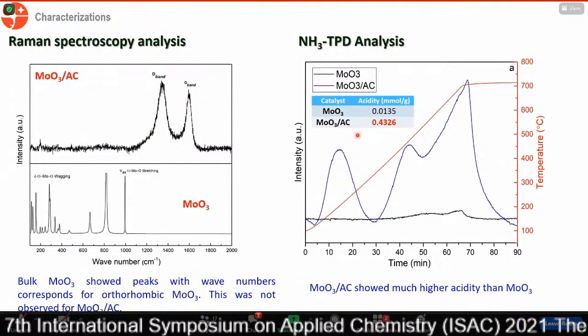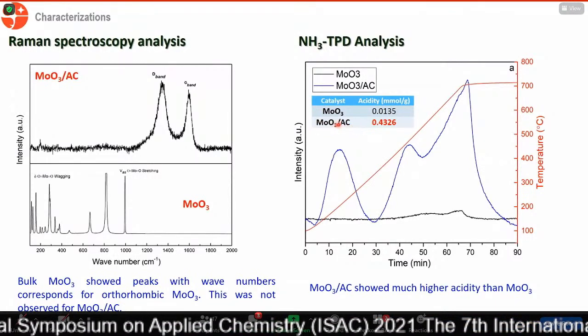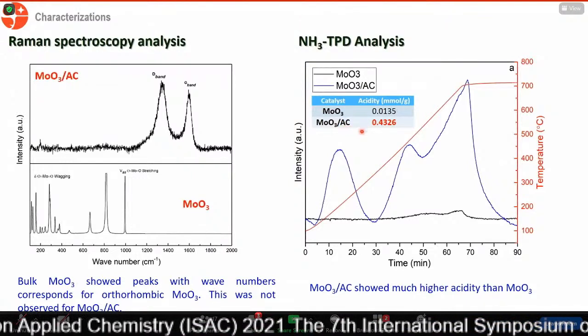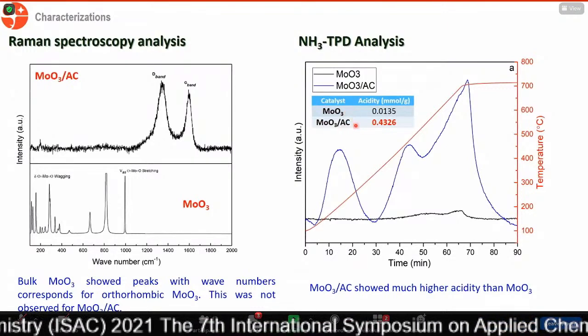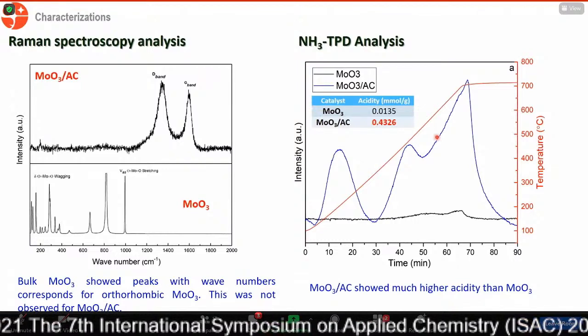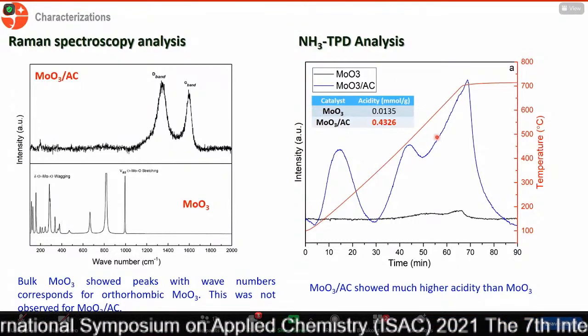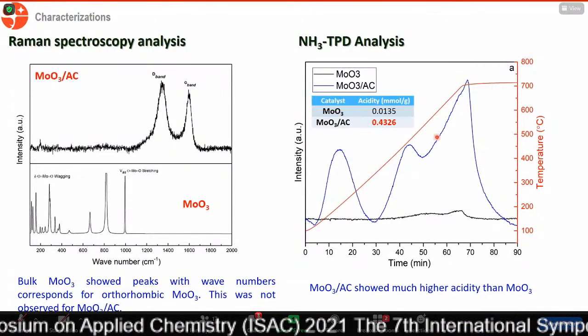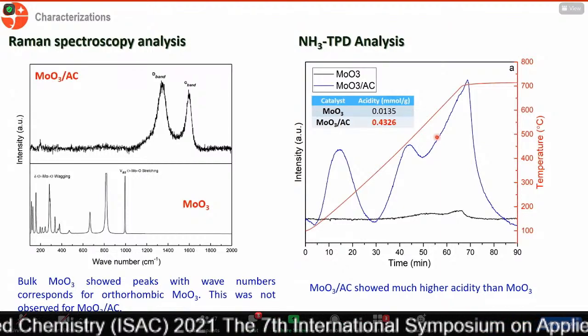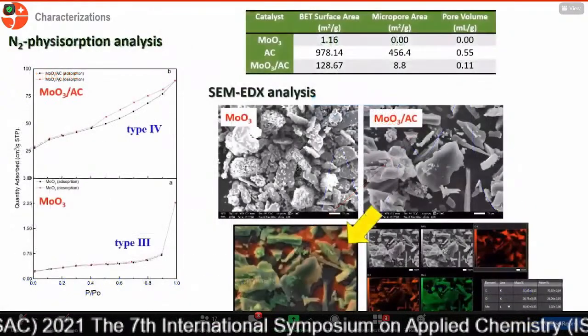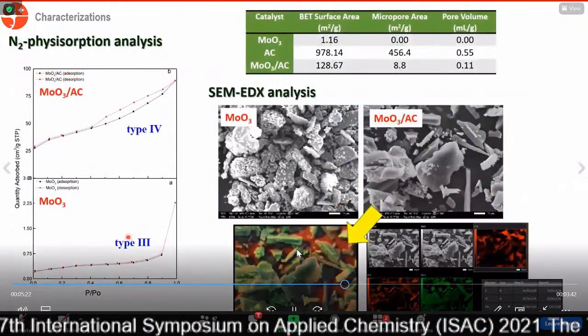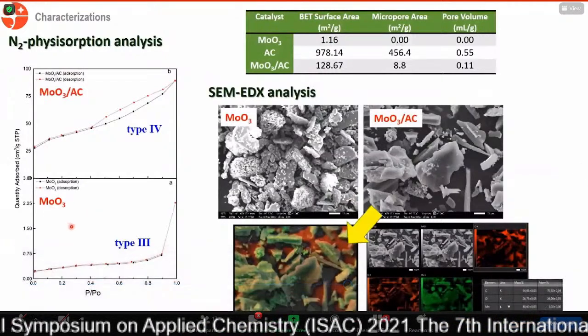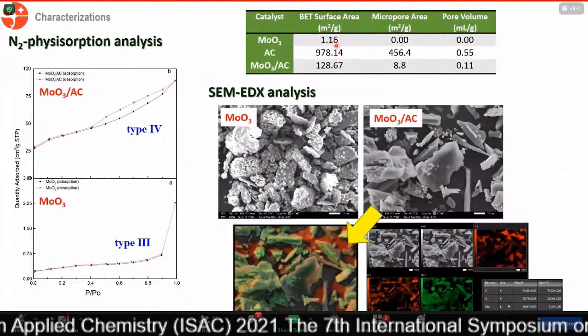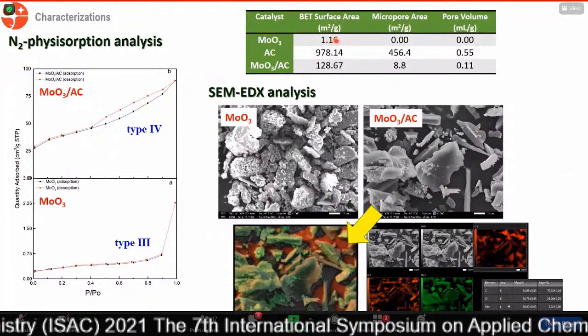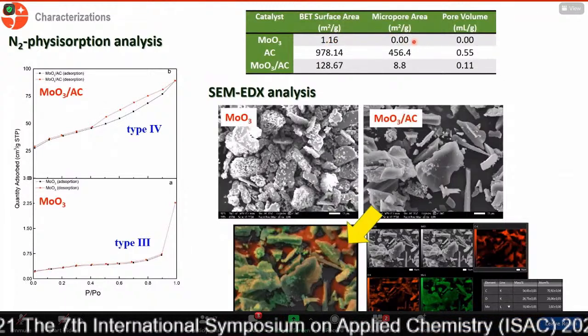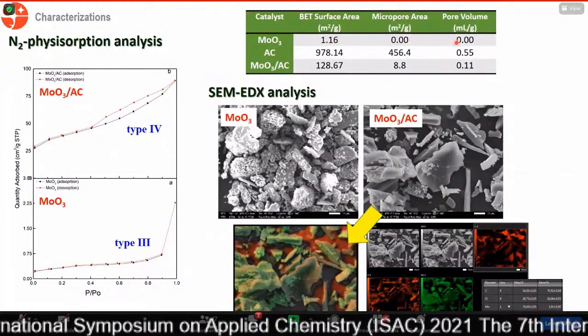And then, as we expected before, the molybdenum oxide on activated carbon shows much higher acidity compared to the bulk molybdenum oxide. Of course, this acidity comes from the acidity of the support itself, which is activated carbon, which contains functional groups that correspond to the acidity of the material. And then, as we mentioned before, the bulk molybdenum oxide is a non-porous material. As we can see here, the surface area is very low, 1 meter square per gram, and it has negligible micropore area and pore volume.